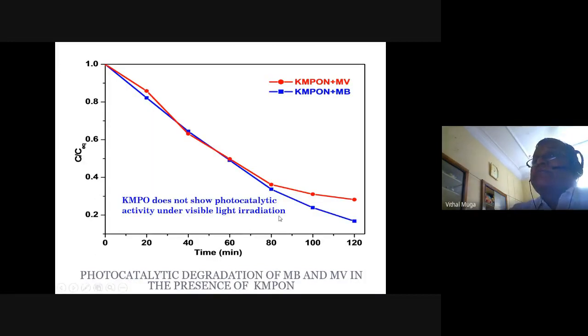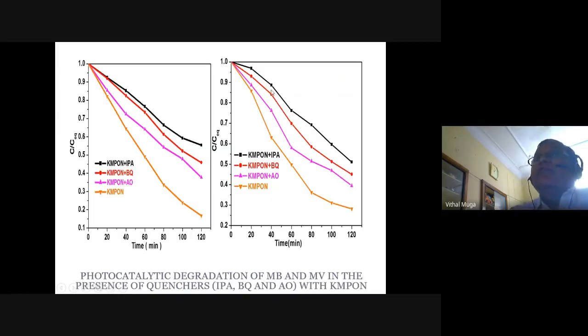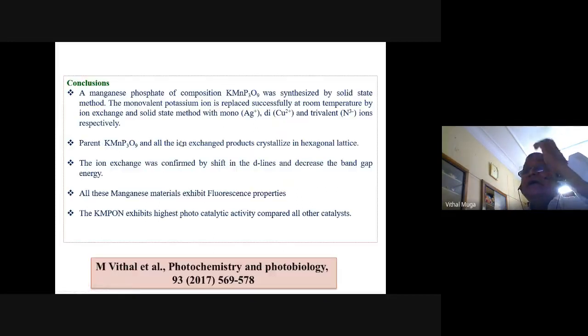Now this is important. KMPO, the parent compound, does not show photocatalytic activity under visible light irradiation, but the nitrogen doped one shows visible light activity. Now you see that it has decomposed about 70, and this has decomposed about 80% of the dye degradation by the N-doped material. Now for the N-doped material, once again scavenger tests have been carried out, and it shows that holes, superoxide radicals and hydroxyl radicals are all actively participating. These are some of the conclusions drawn from this.